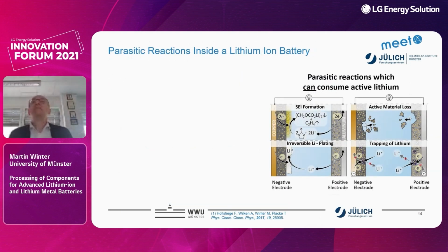So if we are looking at the lithium losses, a lot of people believe that the lithium loss is equal to the charge that is lost in the cycle, especially during the first cycle, but also in the later cycles of lithium-ion battery cycling. And we have indeed a lot of parasitic reactions which occur particularly during charge, which can consume active lithium. For example, we have SEI components which consume active lithium from the cathode. We have also active material loss on anode and cathode side. We might have some irreversible lithium plating. We just talked about the sudden death rollover phenomenon, which leads to this. And also we have the trapping of lithium, because some of the materials that we are using in anode or cathode do not release all the lithium that is inserted. These are all parasitic reactions which can consume active lithium.